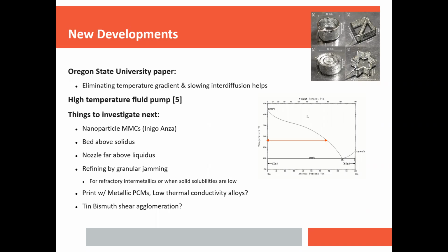Has anyone tried ceramic nozzles? I have looked into ceramic materials for nozzles. Generally speaking, ceramic to metal wetting for molten metals is poor. You need a ceramic that has metallic character. So, for example, the borides or carbides. Titanium diboride, depending on the metal, can work really well. And any transition metal boride, molybdenum boride, chromium boride, chromium carbide. But yeah, it depends. And the metallicity of the ceramic really helps. You need to match your lattice constants kind of at the interface, or you want to match surface energies, but also at high temperatures, the specific chemistries of the metals are very important too.